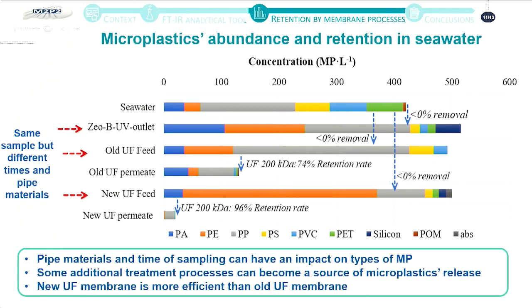If we look at the ultrafiltration at the end of the line, you can see that the new UF membrane seems to remove microplastic better than the old UF, probably also because of degradation of plastic pipes of the pilot plant, or permeate pipes.